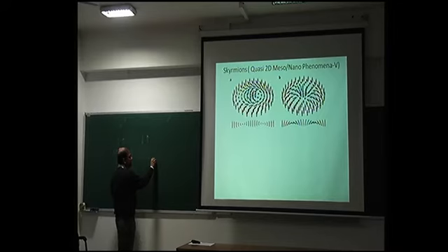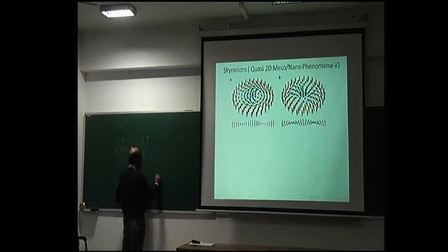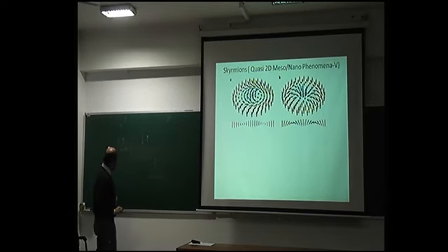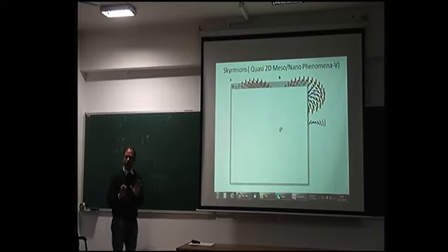But there is another class of materials where this interaction can be anisotropic. Suppose a Hamiltonian based on the dot product of 2 vectors; you can think of why we should not consider a cross product of 2 vectors. And I'm quite surprised that it was not discussed in the physics community until recently, till a few years ago. Skyrme first showed it in a certain problem in nuclear physics. If we ask the question, instead of this, we can write the Hamiltonian this way: Dij, which is a kind of vector, let us assume for the time being, though it's not exactly a vector, it's a tensor, and then Si cross Sj. So this could be another type of interaction. This is called the DM interaction, the Dzyaloshinskii-Moriya interaction.